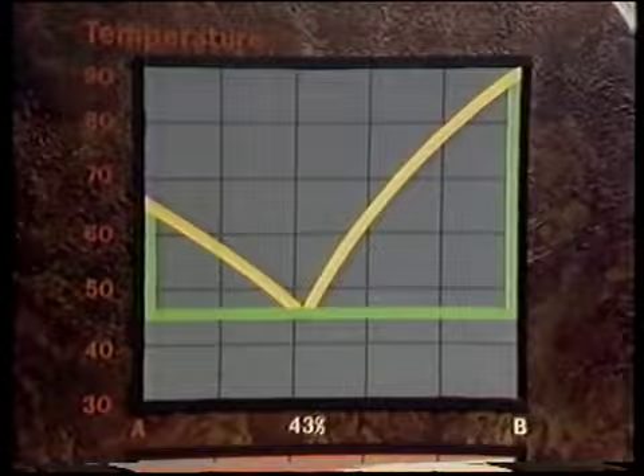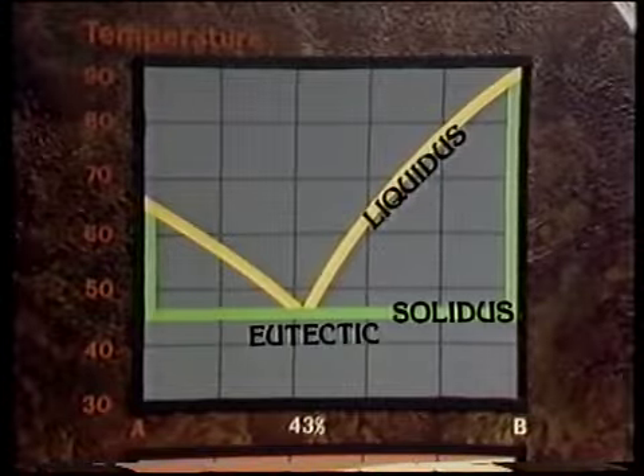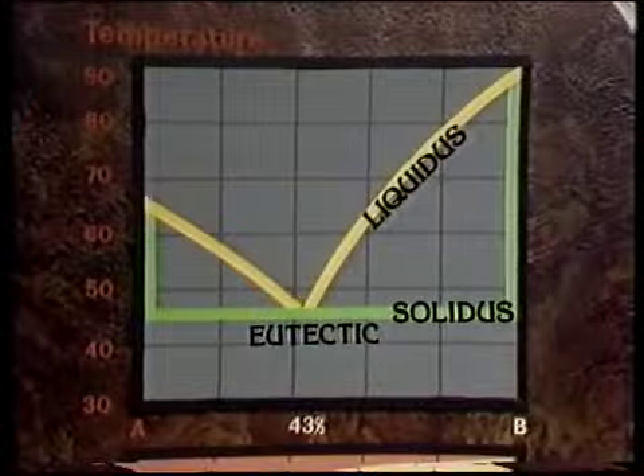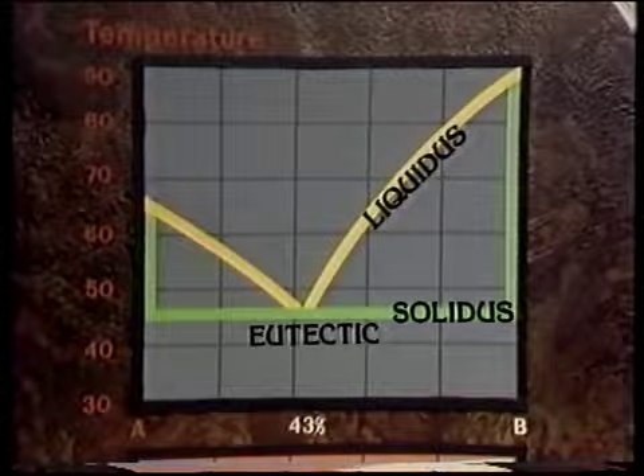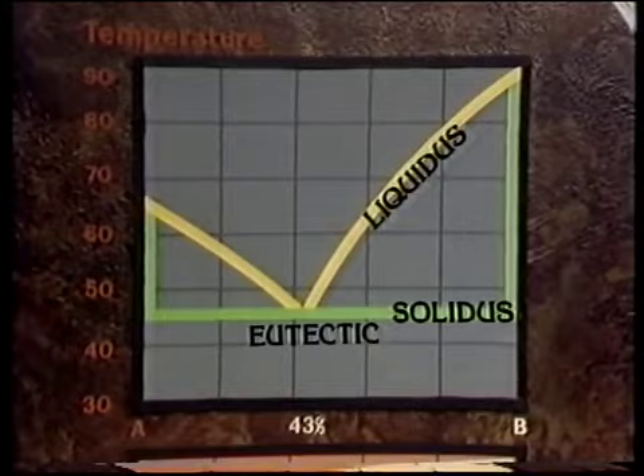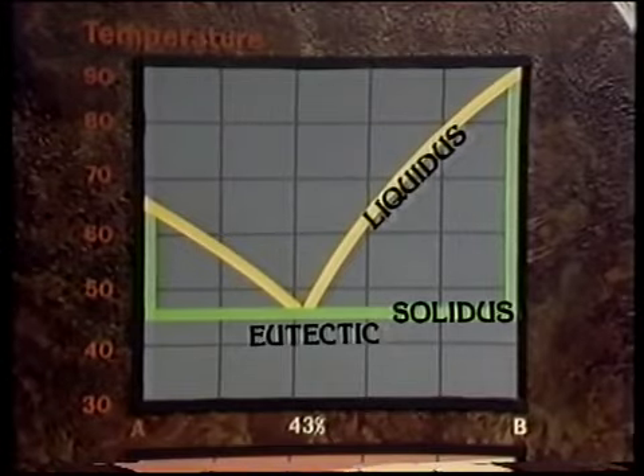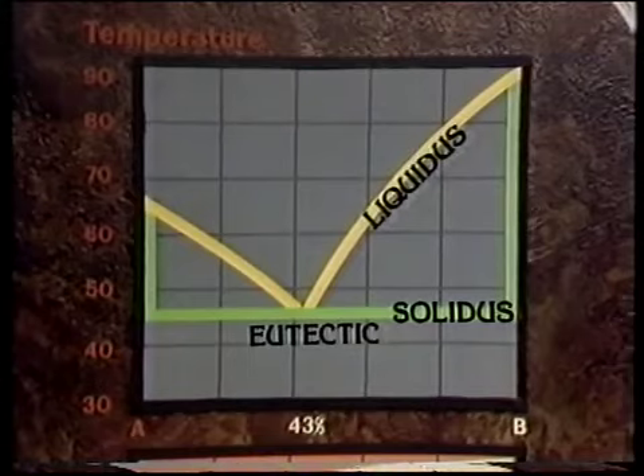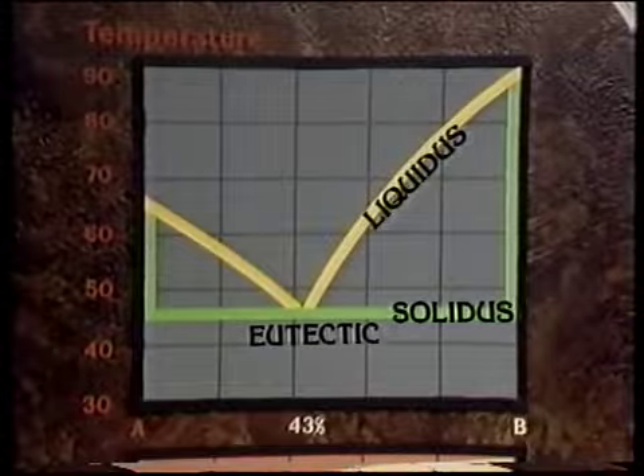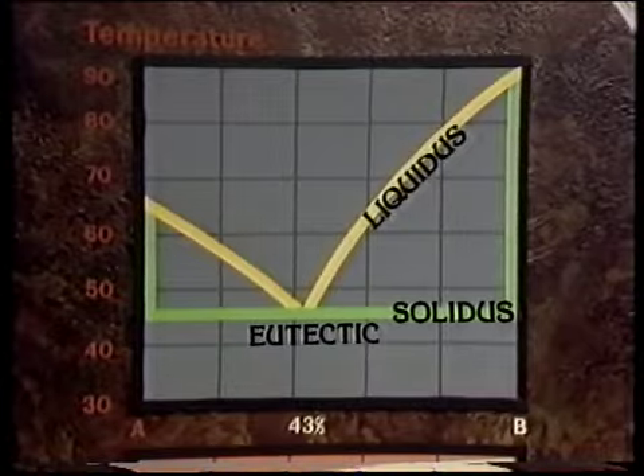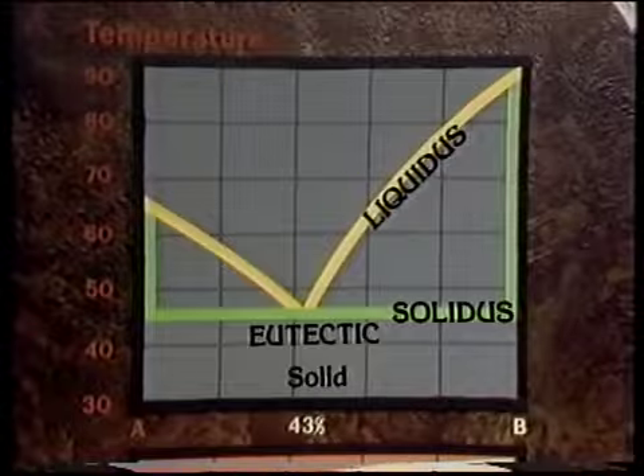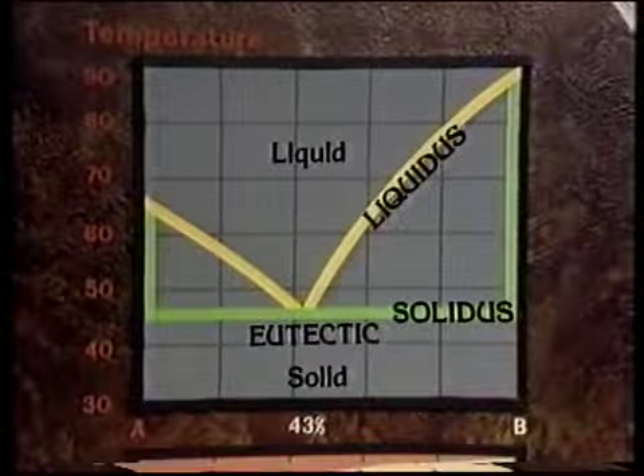These are the three important features. The liquidus defines the crystallization temperatures for molten mixtures of all proportions of A and B. The eutectic point represents the composition which crystallizes and melts at the lowest temperature. And notice that the solidus goes up each side to represent the melting of pure A and pure B. The horizontal part of the solidus tells us that all mixtures of A and B start to melt at the eutectic temperature. So below the solidus, all mixtures are solid, and above the liquidus, all mixtures are liquid.